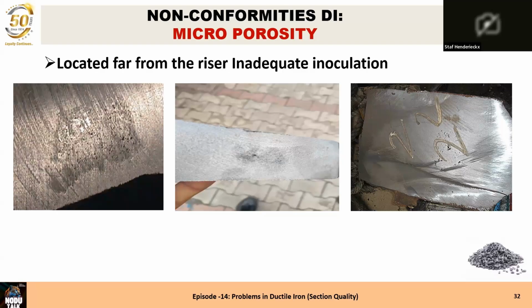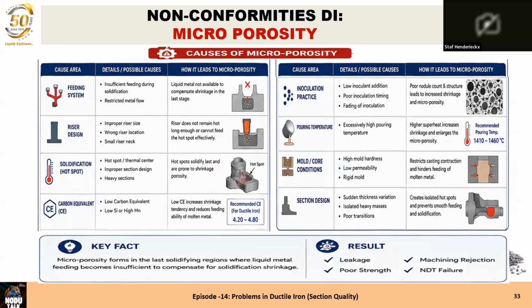Because I said that if your inoculation is inadequate, your nodule count is mostly too low, and a low nodule count will decrease the feeding length of a riser, and you will get these problems at the end of the feeding length or between two risers. So when the feeding lengths of both risers touch each other, then it will be there in the center of the two risers.